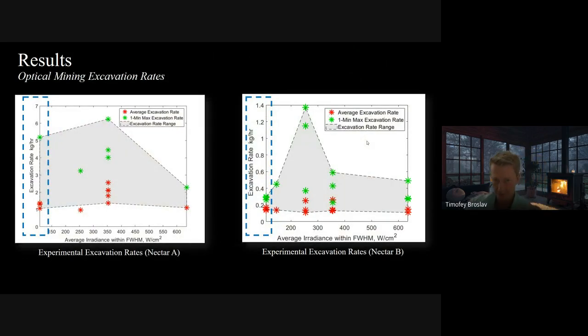Now, regarding excavation rates, you would have a max and an average rate. The max was obtained from instantaneous load cell readings that were averaged over 1 minute. The average values were obtained from using the mass of the Nectar simulant before and after, dividing by the time of light on the sample. Of course, the instantaneous rates are higher because they weren't really constant, because there's a lot of things happening that mess up the excavation rate, like the coating on the glass, for instance.